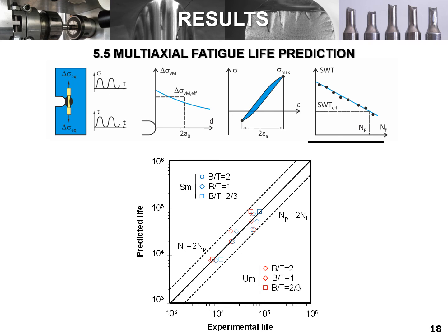This figure compares the predicted values with those determined in the experiments for the different BT ratios. Overall, as can be seen, there is a very good correlation between the data. In addition, predictions are within scatter bands of 2. Finally, it is also clear that the predictive capabilities of both approaches are similar, which is an interesting outcome.